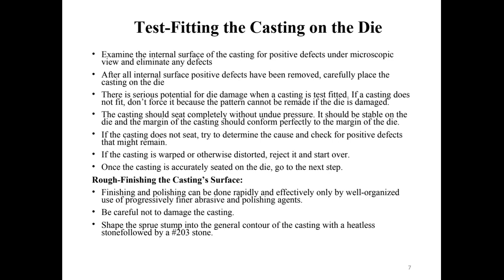So, how we test fit the casting on the die. Examine the internal surface of the casting for positive defects, so bubbles, under the microscope and eliminate any defects. After all the internal surface's positive defects or bubbles have been removed, carefully place the casting on the die. There is serious potential for die damage when a casting is test fitted, so we have to be very careful. Do not push or force the casting on the die.